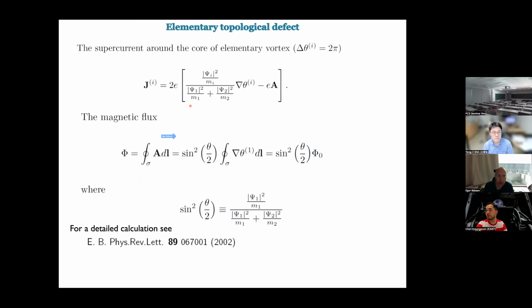If you just use the absolutely standard calculation for the magnetic flux of an ordinary vortex, you write the superconducting current in component i and in component j. Now there is phase winding only in one component, but not in the other. Then the current has this prefactor. And if you want to calculate the flux of a vortex, you integrate the vector potential over a contour. Then you find that this elementary vortex carries a fraction of the magnetic flux quantum. And it costs logarithmically, or in a more general model linearly, divergent energy per unit length.